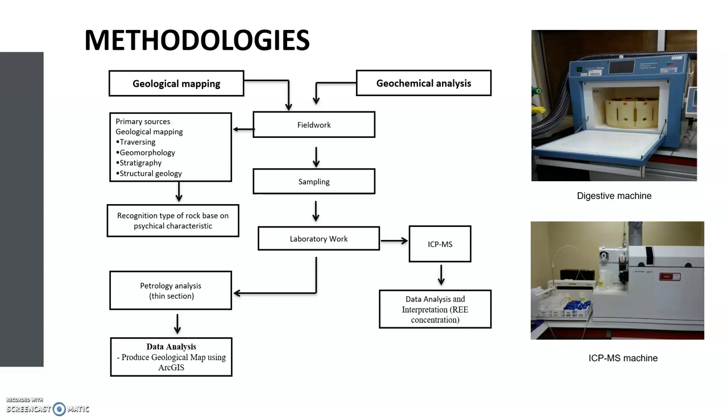Inductively coupled plasma mass spectrometry (ICP-MS) is an analytical technique that allows more sensitive detection over a wide range of elements, with an extremely low detection limit of atomic elements below 1 part per trillion. This technique is highly recommended for trace elemental analysis as it offers high speed of analysis, accurate detection limit, and isotopic sensitivity potential.